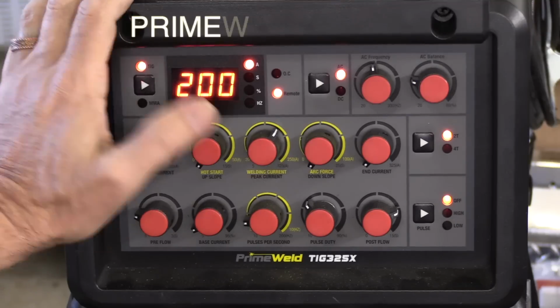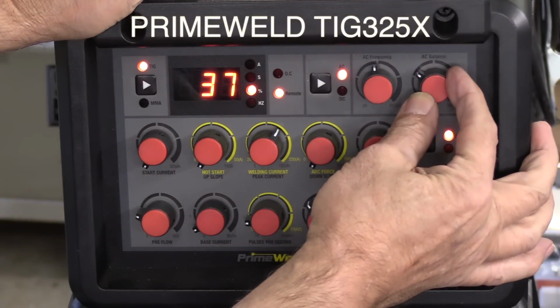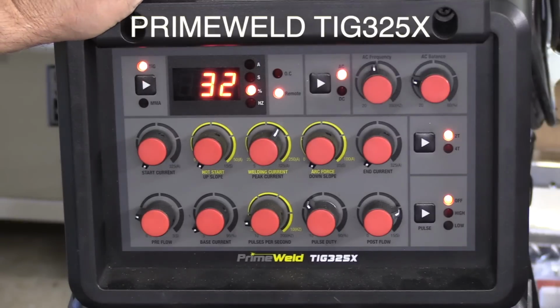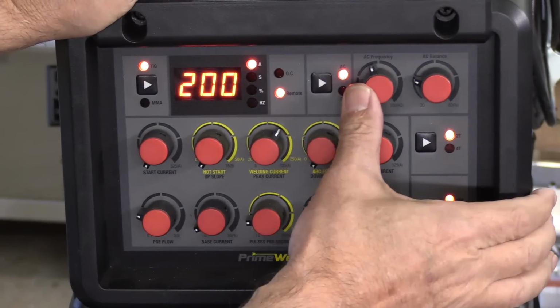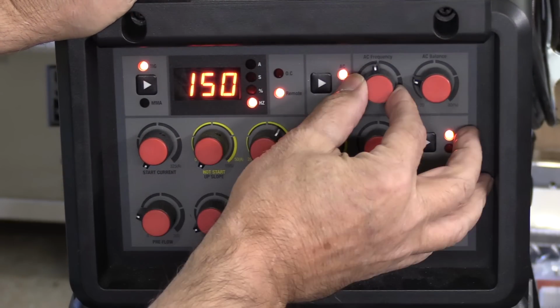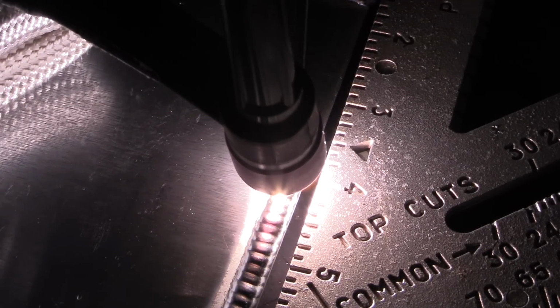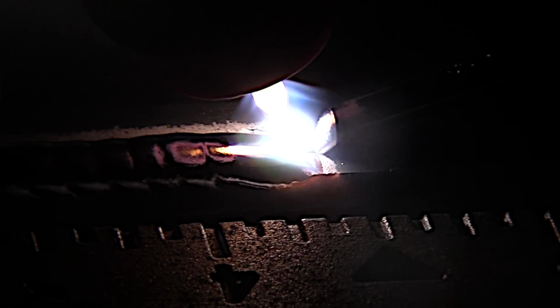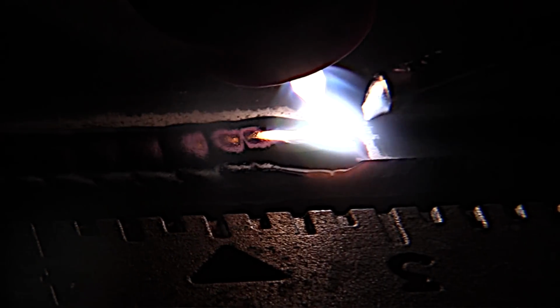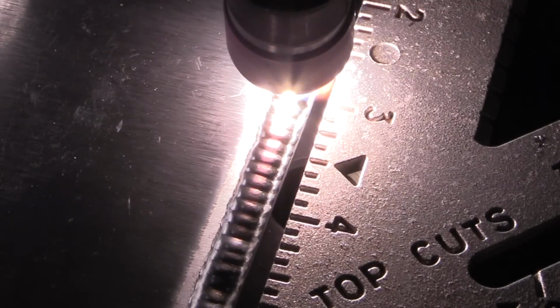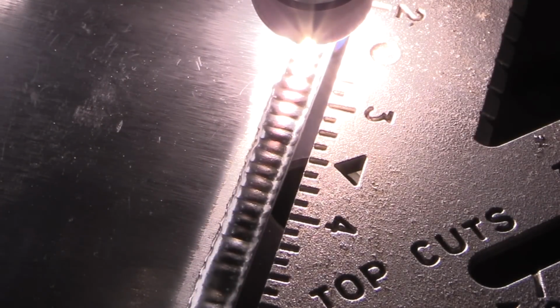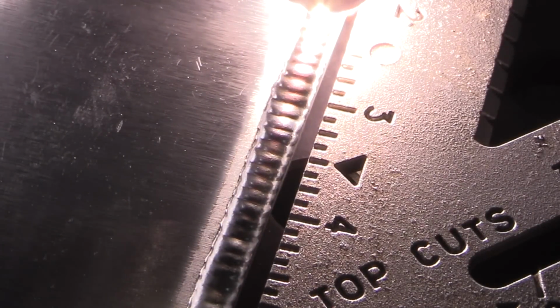Since I'm using a foot pedal, I'm going to set the machine amperage to 200, AC balance to 32% cleaning, a good all-around setting, AC frequency to 150. For this first bead, I'm going to be trying to do 1/8 of an inch of travel per second, 1 dab per second. I'm using 1/8 of an inch thick 4943 filler metal. I was going to use 5356 filler metal, but I had some extra 4943 that was given to me by a local welding supply as a sample. It's Hobart filler metal. Got a lot of benefits and I like it.